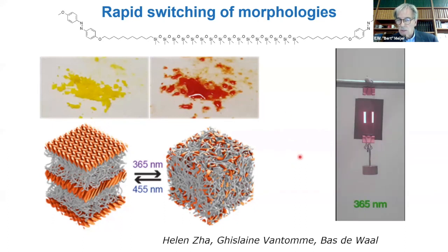And we shine light on it, and now the laser will come. Light source, 365, and you see it becomes a liquid. We say, oh, stop, because now it's back here. And if we shine light on it again, it falls off. So really, it's almost instantaneously going from crystal to amorphous back to a crystal. And that is due to the incredibly high chi parameter, so insolubility between the two units. And as a result, the crystallization goes extremely fast.